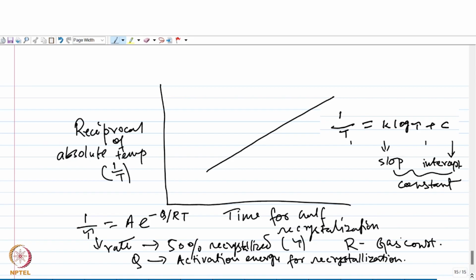Right? So through such plots also the effect of temperature can be seen. So from here you could see that as the temperature is increased, the time required for 50% recrystallization decreases. Okay, and this tau can be for any fraction. It doesn't have to be 50% all the time. It could be any fraction of the recrystallization, and from that you could see the effect of temperature as to what is the time required for a particular fraction of recrystallization at a particular temperature. And with that, we come to the end of this lecture. Thank you for your attention.